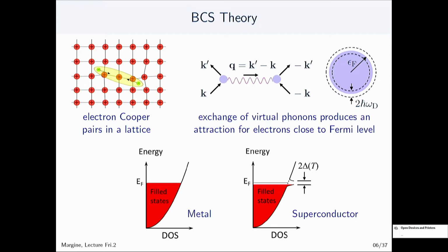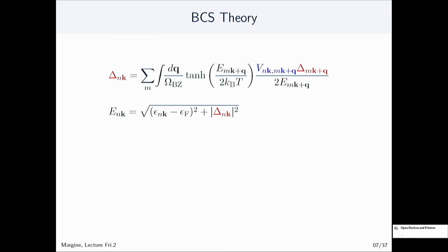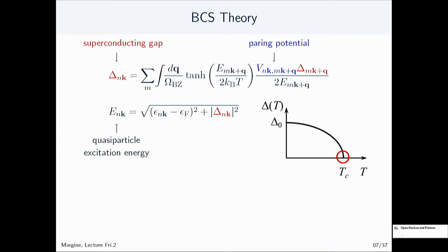So the smaller the characteristic phonon frequency of the material, the longer the time it takes for an ion to reach this displacement, so the longer the retardation. This retardation effect is missing in the BCS model. It's considered that the electron-phonon interaction is basically instantaneous.